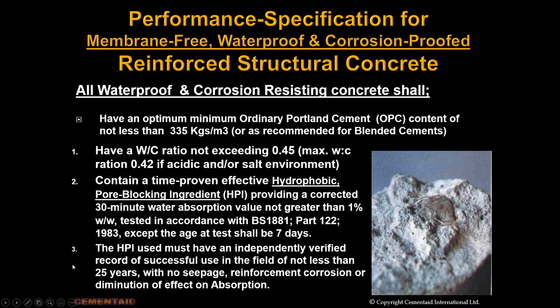That 0.3 is so important. As I said, there are a lot of so-called integral waterproofers for concrete that will work extremely well when tested in a laboratory, and they will pass this BS 1881 part 122, but they won't necessarily do that for much longer than a few hours if you look at the way the test is done.